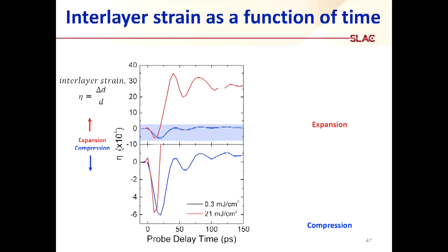Yes, a very particular type of phonon, actually, because you'll see the time scale is pretty slow. It's about 10 picoseconds or something. So it's not the interlayer breathing mode, which is actually quite fast compared to this. It's a low frequency mode, but a typical vibrational frequency would correspond to something like 50 femtoseconds or so. So this is actually a kind of acoustical shock wave where you don't deposit the energy completely uniformly. You heat up the front of the sample a little more, and then the shock wave propagates back and forth. We know that very well because from that X-ray measurement I showed you, we know exactly how thick the sample is. We know the speed of sound. You can compute the period, and that all lines up very well. So you can explore that kind of regime of impulsive launching of acoustical waves.